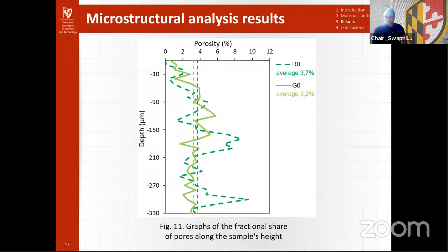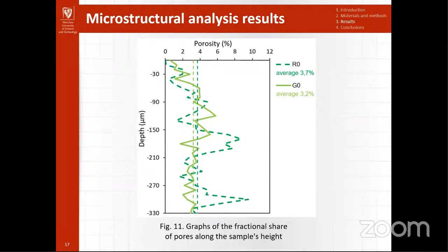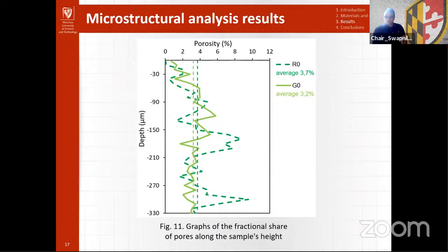Then we constructed the porosity plots shown in Figure 11. In this graph, it can be seen that the R0 sample from the raw surface is characterized by a slightly higher porosity of the subsurface layer of the substrate compared to the sample from the ground surface.